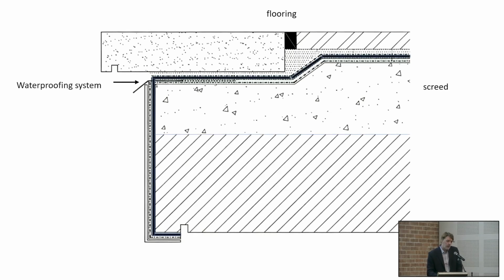The best way we may recommend to you in a project to avoid this problem is to place the waterproofing system just under the tile. Not only on the structure, just under the tile. The waterproofing system like the last layer before fixing the tile. In this case, when it is raining or when you wet the surface, the water will penetrate into the joints, but will immediately be stopped by the waterproofing system. And in this case, all the stratigraphy below will be completely dry, with no rising damp, with no excess of water inside, and so with no efflorescences.